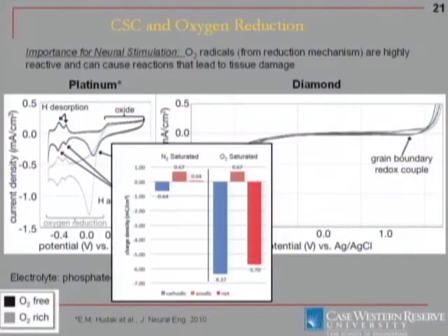So what that means, if I calculate the charge storage capacity, which might predict how much charge it's going to inject and also how reversibly the charge will be injected, this is platinum. And what you have here is, here's the cathodic charge, so going in this direction, going negative. All the current that's below 0 would be the cathodic charge. If we look at the positive charge, it is all the anodic charge going in the positive potential region, current that's above 0. And those are pretty well equal in a nitrogen-saturated electrolyte, PBS.